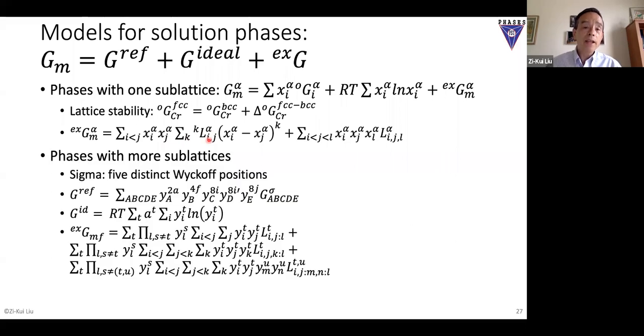However, for the phases with more than one sublattice - for example, sigma phase, sigma has 5 sublattices, okay? 5 distinct Wyckoff positions, so it's a pretty complex structure. In that case, you have to do the 5 sublattices - they have 5 sublattice entropy, they have 5 sublattice interactions. So that now becomes much more complex.